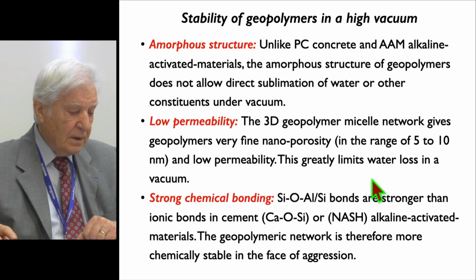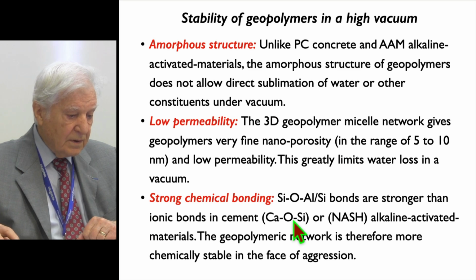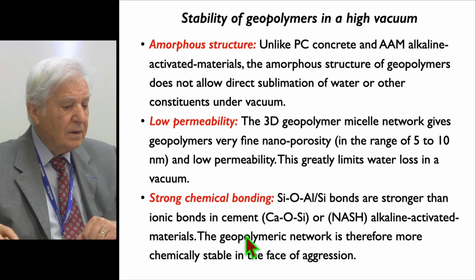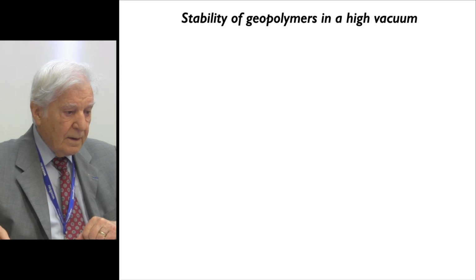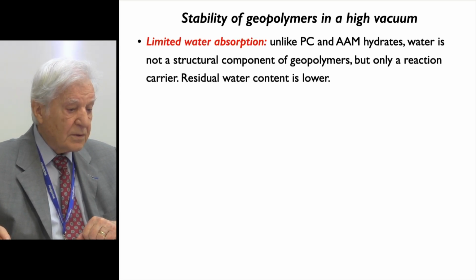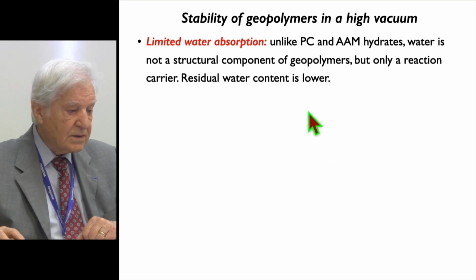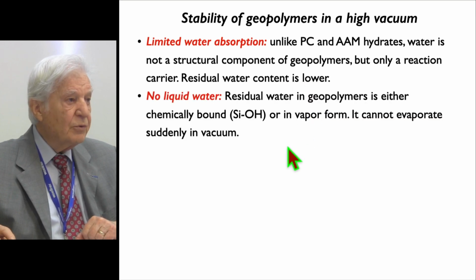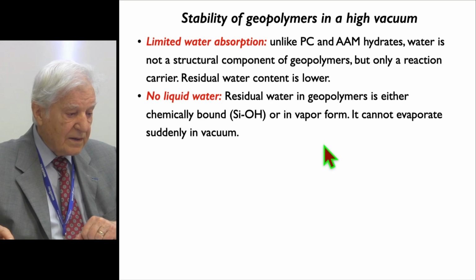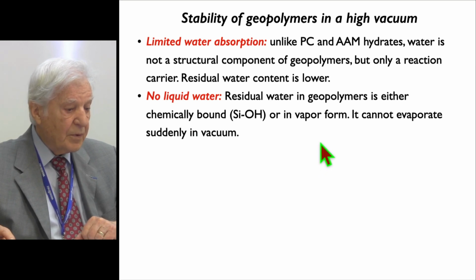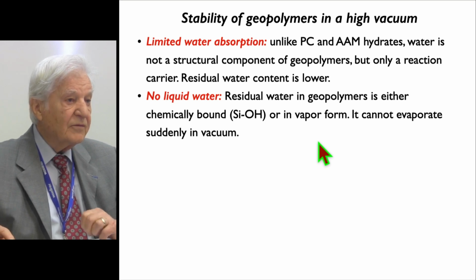Strong chemical bonding. The Si-O-Al or Si-O-Si bonds are stronger than the ionic bonds in cement, calcium-oxygen-silicon, or N-A-S-H alkali-activated materials. The geopolymeric network is therefore more chemically stable in the face of aggression. Limited water absorption. Unlike Portland cement and alkali-activated hydrates, water is not a structural component of geopolymers, but only a reaction carrier. Residual water content is lower. No liquid water. Residual water in geopolymers is either chemically bonded Si-OH or in vapor form. It cannot evaporate suddenly in vacuum.